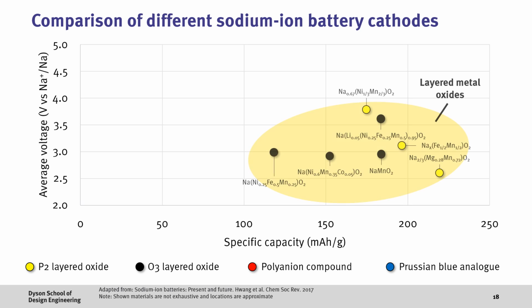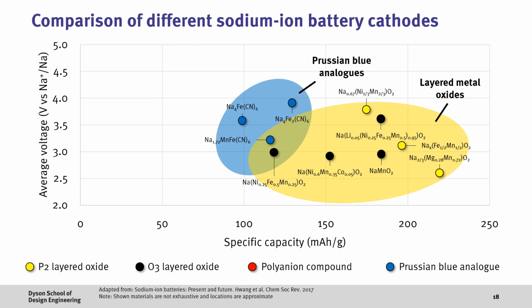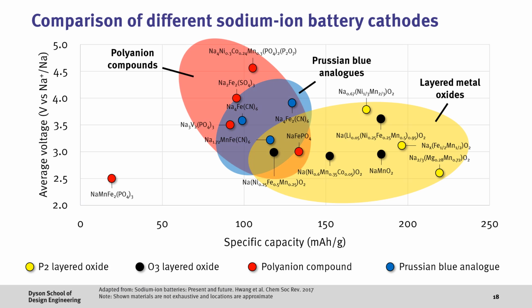To visualize how each class of materials compares against each other, this plot shows the typical average voltage of each cathode with their general specific capacity. Note that the exact numbers can vary depending on a range of factors. For the metal oxides, which we can break down into P2 and O3 type materials, these generally have the highest specific capacity. Prussian blue analogues have somewhat lower specific capacities, but have a more theoretically stable crystal structure which can give better lifetime, not shown on this plot. And the polyanion compounds generally have the lowest specific capacity, but highest voltage and improved safety, again not shown on this plot. Again, it's important to note that not all possible materials are shown here.